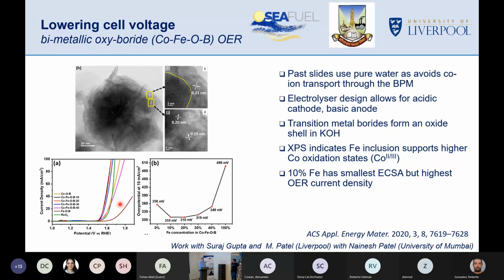And what we're seeing here is actually the beneficial behavior of the core. I think we're just seeing a very thin shell of active catalyst and then the core supporting the device. So I think it's like having a very thin cobalt oxide catalyst over a conductive core. I don't think we've fundamentally changed the chemistry of the surface, despite some papers saying otherwise.